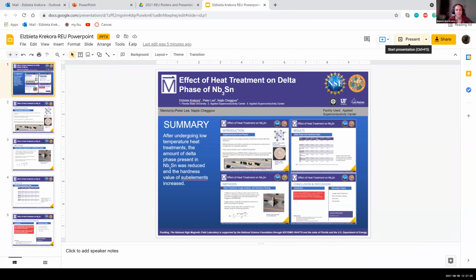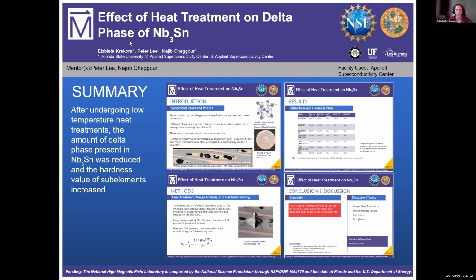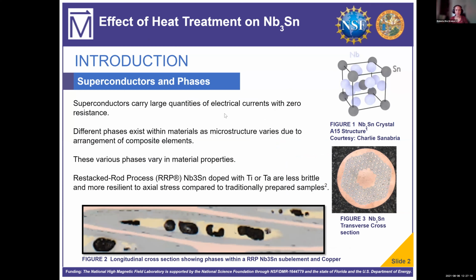This summer, I spent it studying the effect of heat treatment on the delta phase of niobium 3 tin. My mentors were Dr. Peter Lee and Dr. Najib Chagor, and we found that this heat treatment could reduce the amount of delta phase present in niobium 3 tin subelements and also increase the hardness values.